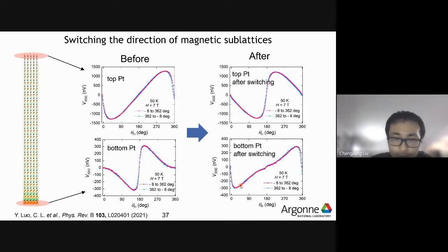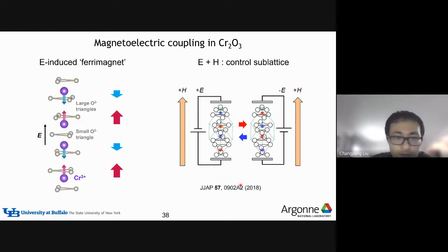So now we further found that the spin current we measure here is due to the magnon spin current, and because chromium oxide has a special property called magneto-electric coupling. Basically, this means a magnetization could be induced by applying an electric field along the z-axis. This is due to the special crystal lattice of chromium oxide.